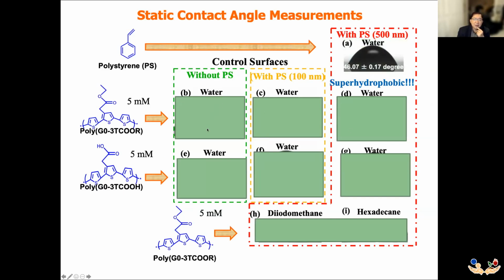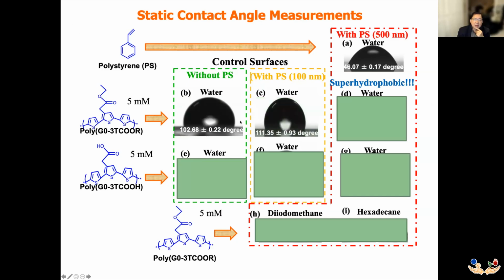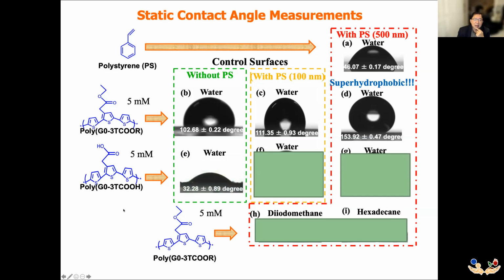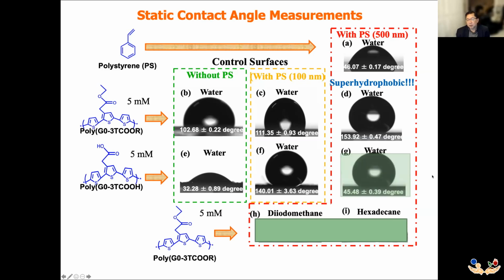If we pattern them without the polystyrene, you can see the ester-containing polythiophene group having a decent hydrophobic effect. Once we add the 100 nanometer particle array, we have an increase in the contact angle. But then when we pattern it with the 500 nanometer latex particle, we observe routinely a superhydrophobic behavior. Now, what if you change the ester with an acid? You'll end up with a nice wetting behavior, but with patterning, it actually converts it into a hydrophobic surface as well, as can be shown here.